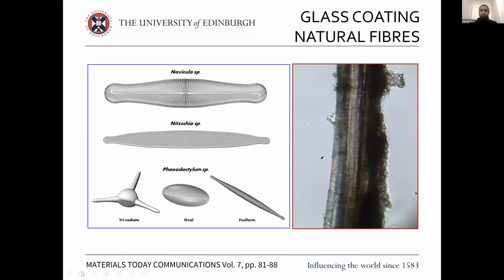Some of them didn't. It depends on the type of fiber you're using. It depends on the kind of diatom that you're using. But what's important is that where we did manage to coat the fibers in glass, we improved quite significantly the mechanical properties of the fiber. And normally you cannot coat natural fibers with glass, because natural fibers have a decomposition temperature of about 300 degrees Celsius, whereas glass will melt at around 1500 or so degrees Celsius. So it's very unlikely. And I think the diatom bioglass actually melts at higher temperatures still, from what I've understood. So this is a clever way of improving the mechanical properties of the fibers themselves.